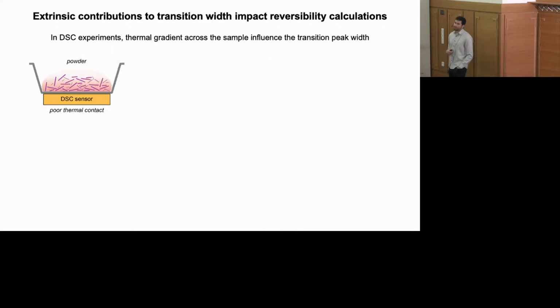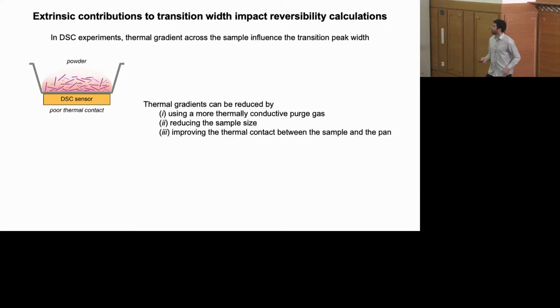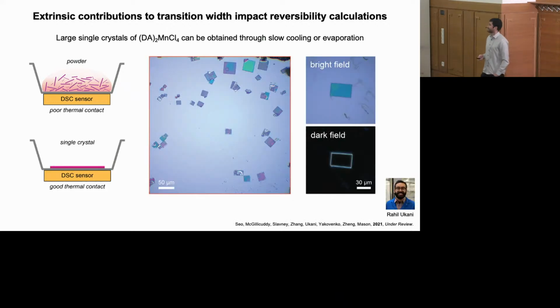But what we found is that for these 2D perovskite materials, as two-dimensional materials, they tend to form really large flakes that stack together, but do not pack together particularly well, and do not have really great thermal contact with their surrounding environment. And this leads to thermal gradients as you're increasing and decreasing temperature that broaden the phase transition.